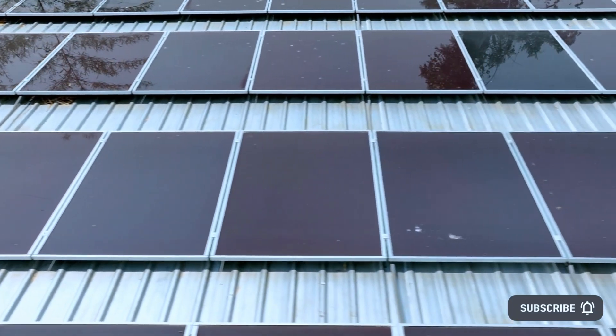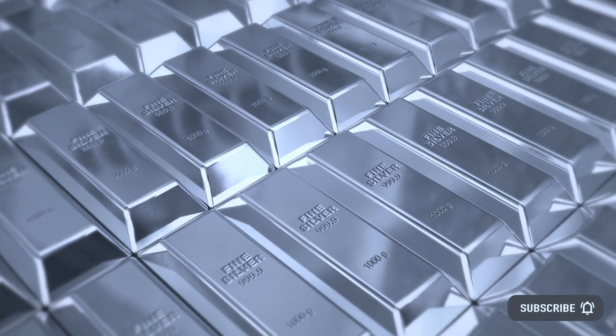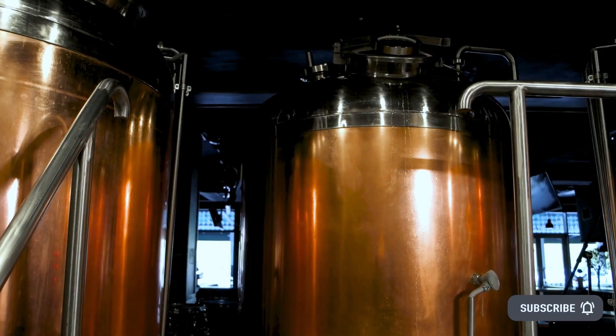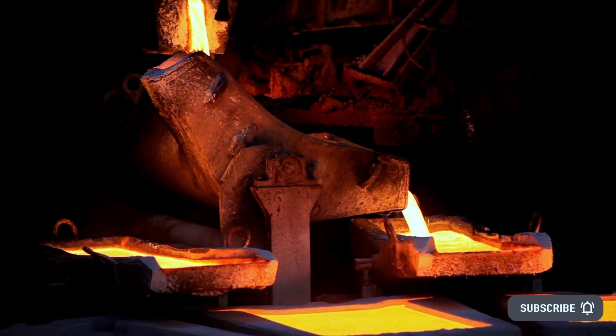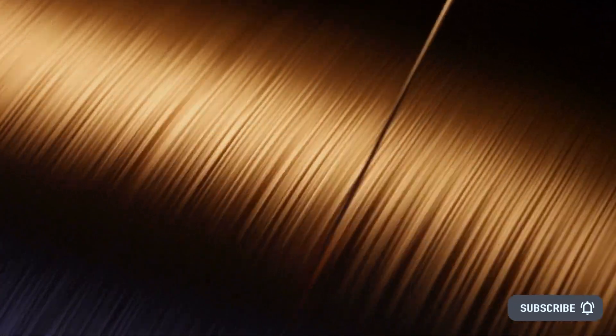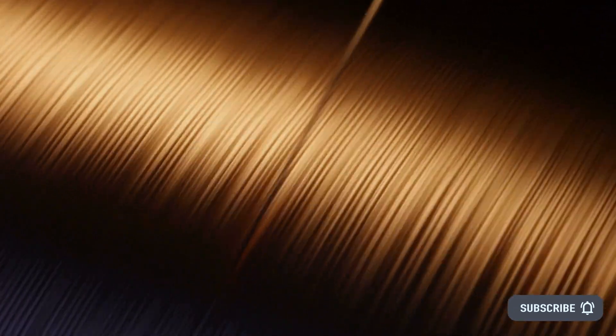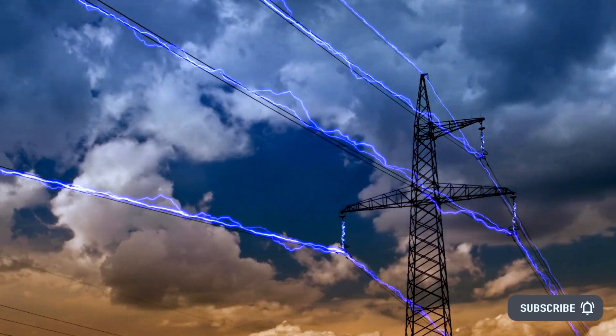The researchers developed a special electroplating process that makes it possible to use copper instead of silver for the busbars, which even improves conductivity. The copper contact lines are particularly narrow on account of their laser structuring. Due to the copper lines' extremely small width of only 19 micrometers, the light-absorbing silicon layer experiences less shading than with the silver lines. This, combined with the high conductivity of electroplated copper, improves the electricity yield.